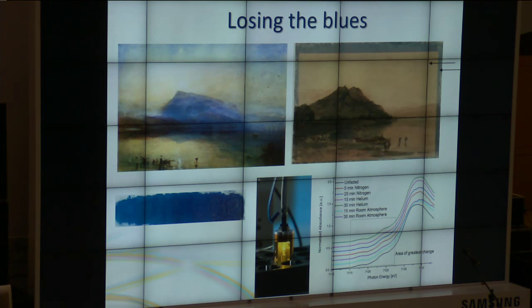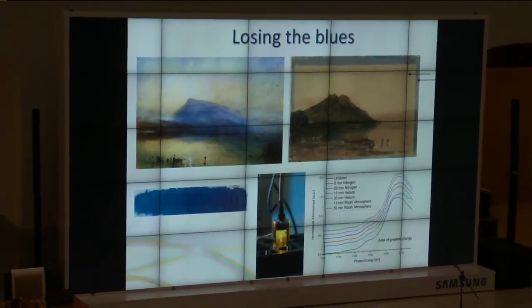To cut a long story short, some of the work we've been doing at Diamond is looking at the mechanism of the fading process of Prussian blues. We've tried to accelerate that by exposing the Prussian blue to very bright light and then seeing with spectroscopy how the chemical structure changes according to whether you do it in oxygen or under other gases. And what we've demonstrated through an accelerated aging process, where we simulate decades and decades of exposure to sunlight using very bright light, is that in the case of Prussian blue, the removal of oxygen is not a problem. So this establishes that if you want to stabilize the blues in Turner's paintings, keeping them under an inert gas or a gas without oxygen is almost certainly okay. And the fading that was attributed to oxygen earlier is almost certainly due to an interaction with certain types of canvas or paper.